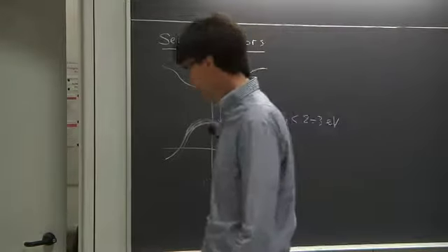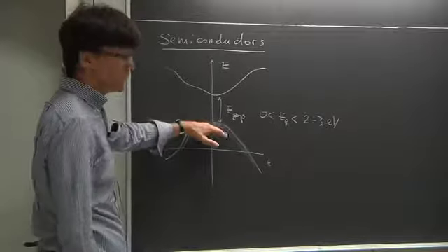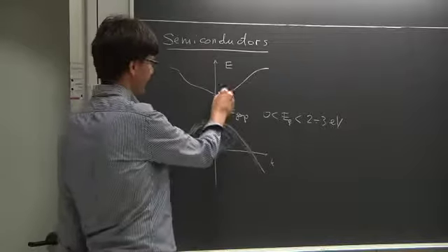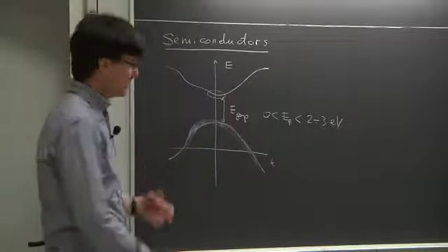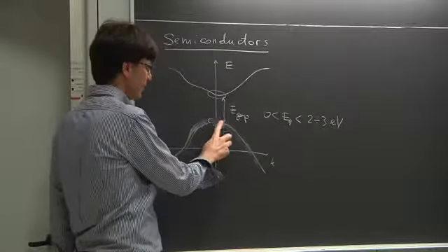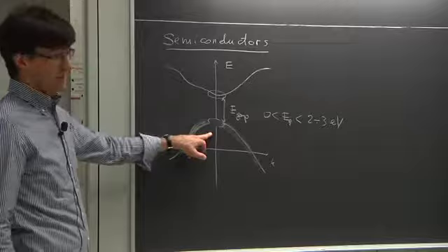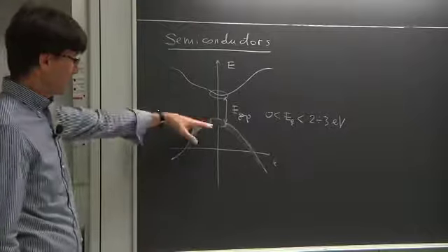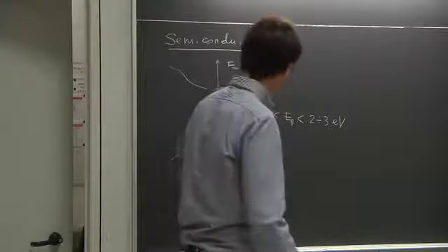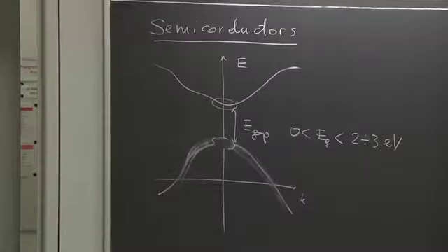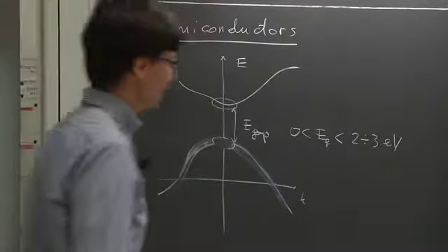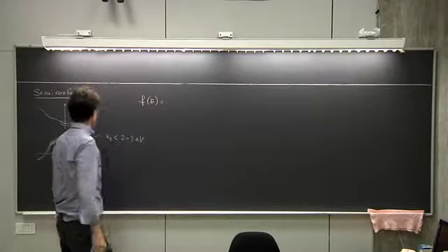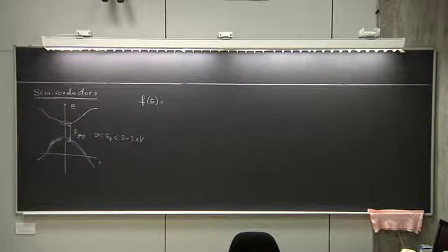The main one being that at finite temperature, there will be a small but finite number of electrons that are excited in this band. And of course, there will be a depletion, right? An absence of electrons in the higher occupied band that at t equals 0 formally would be completely filled. Now, the reason for that is something we've already discussed, although very briefly. So the reason for this is that at finite temperature, we need to fill states according to the Fermi-Dirac distribution.